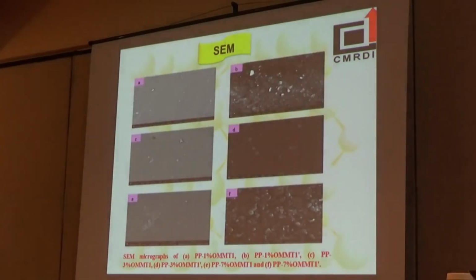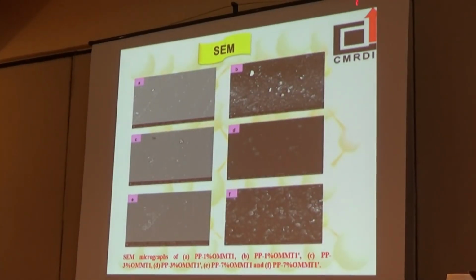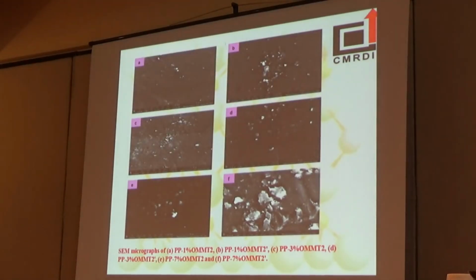Scanning electron micrographs show that in case of absence of compatibilizer, the surface is rough and the clay particles are present as if stuck on the surface, while in case of presence of compatibilizer, there is improvement in the distribution of the clay particles within the polymer matrix. The same trend is observed for the second two series.